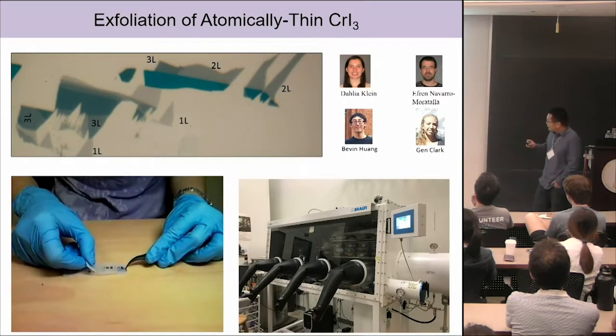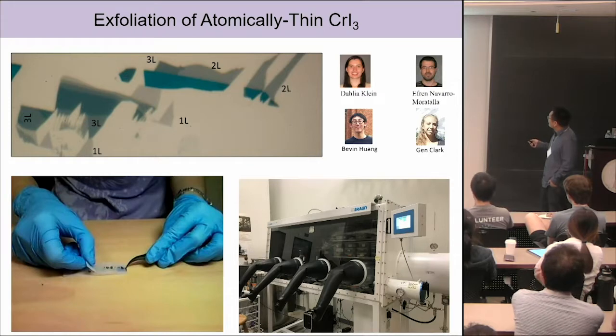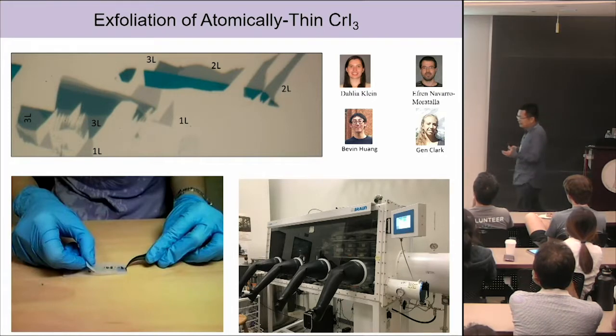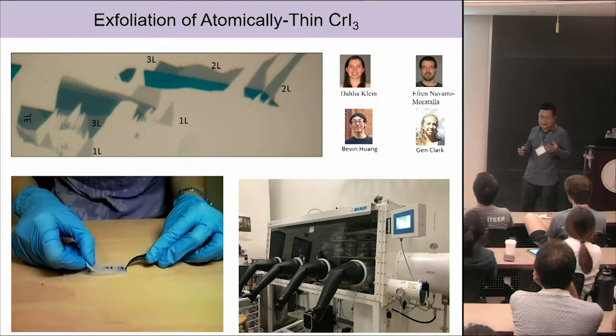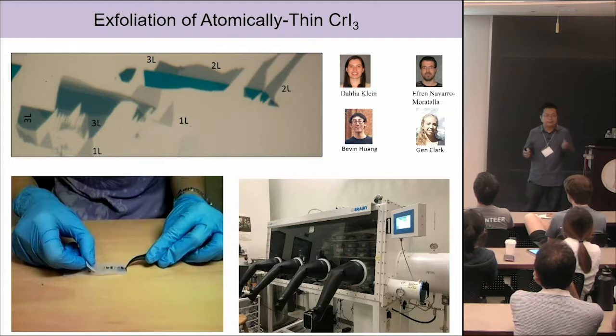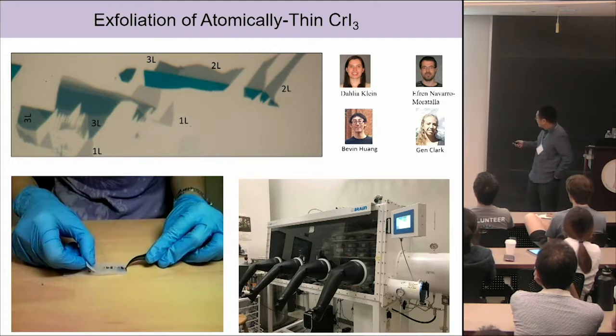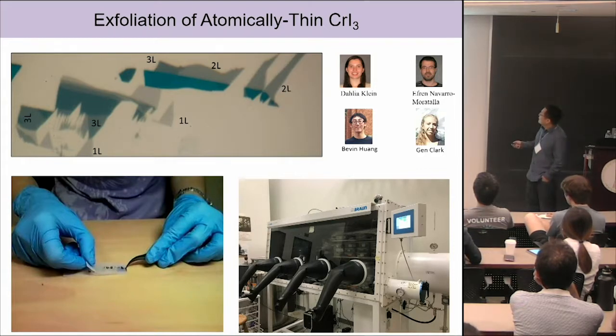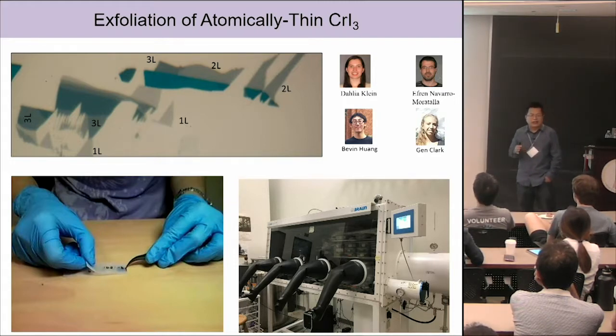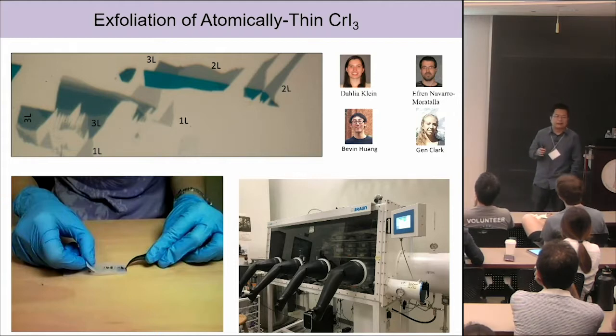We also worked with a collaborator's group to get these monolayers. These 2D magnets are easily exfoliated, but they are also not stable in ambient conditions. So we always work in a glove box. Here I show you optical microscope images of the samples — just by optical contrast, you can already see one layer, two layers, three layers, et cetera. It's quite easy to exfoliate; the only challenge is stability in ambient conditions.